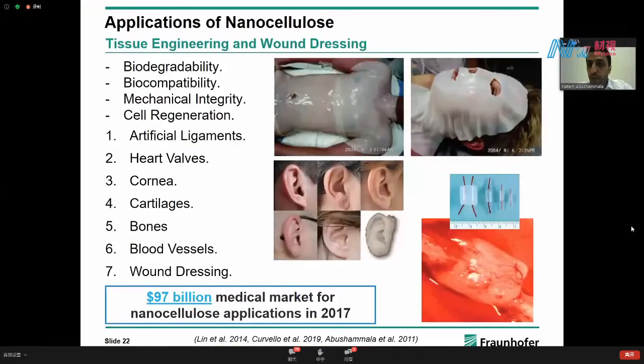For tissue engineering and wound dressing, nanocellulose is also very interesting because it's biocompatible. We talk about mechanical integrity. Also, nanocellulose promotes cell regeneration. And let's not forget biodegradability. For example, if you make a nanocellulose-based material to replace some part of your bone, you would love this part to host the calcification of your bone again through the pores of this nanocellulosic material, and then this material will be biodegraded over time, and you will have a fully functional bone in the place of the nanocellulosic material. Nanocellulosic materials have been explored as artificial ligaments, heart valves, cornea, cartilages, bones, and also to replace blood vessels, and are also very interesting for wound dressing.